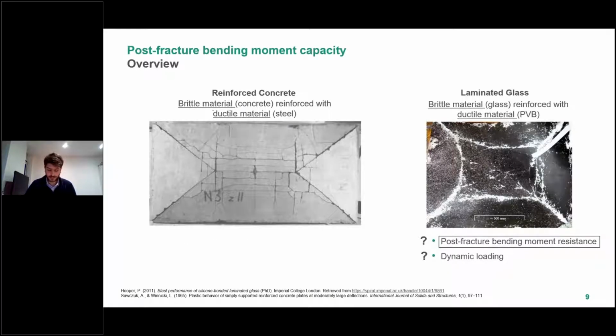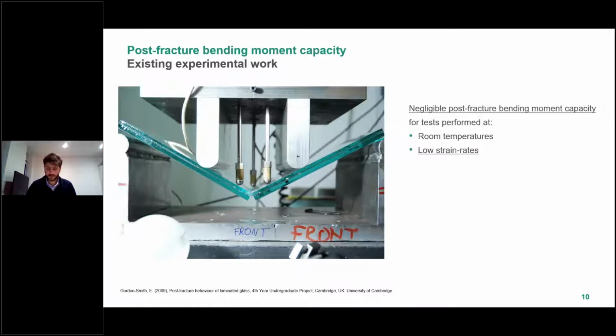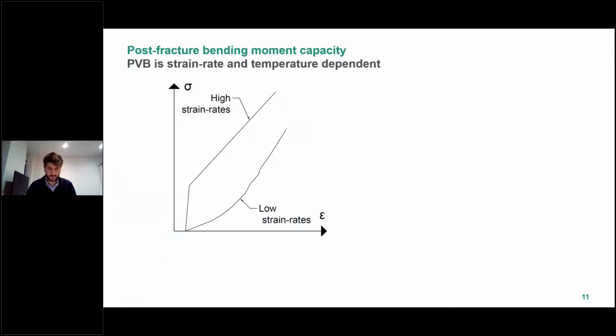Starting with the post-fracture bending moment resistance of laminated glass, previous experimental work on pre-fracture specimens has demonstrated that this is negligible for specimens with polyvinyl butyral interlayers. However, these tests were performed at low strain rates, as opposed to the high strain rates anticipated under blast loading. This is important as the PVB interlayer is a thermoplastic polymer that becomes significantly stiffer at high strain rates. The response under blast loading is therefore fundamentally different compared to the previous experimental work at low strain rates.